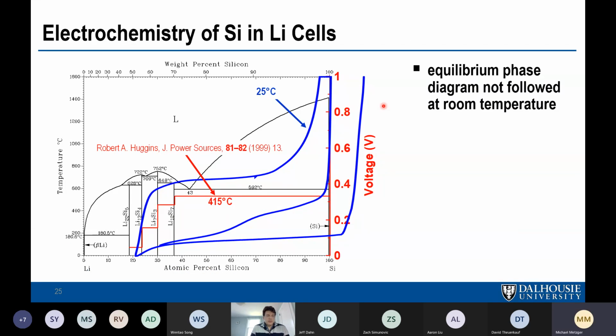Okay, so those are ways of improving performance of alloys. You want a good binder and a good electrolyte additive, and when you combine those things together, you can get a half-decent voltage curve for silicon. You can see a big improvement compared to the one from the 1990s.